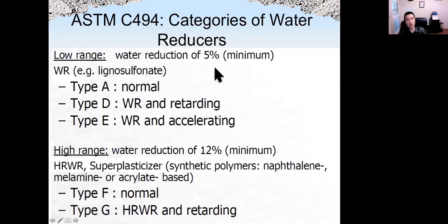So water reducing agent is specified in ASTM C494. We have again many different types: low range, high range, and one or two functions. Type A is normal, low range. Type D is water reducing plus retarding, which means the setting time will be increased, or accelerating, reduce the setting time. So depending on what you want for your concrete, you can choose different types of water reducer.